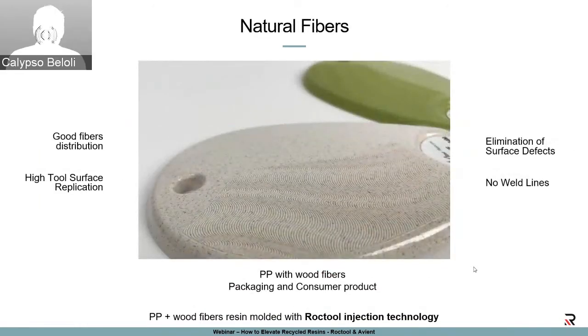And to finish my examples, this is a PP with wood fibers. So the idea is to use wood fibers to achieve some kind of natural part. And in this case, again, normally you will have heterogeneous fiber distribution in conventional, and with Roctool we can achieve a good surface aspect, good distribution, and elimination of weld lines and surface defects like sink marks.